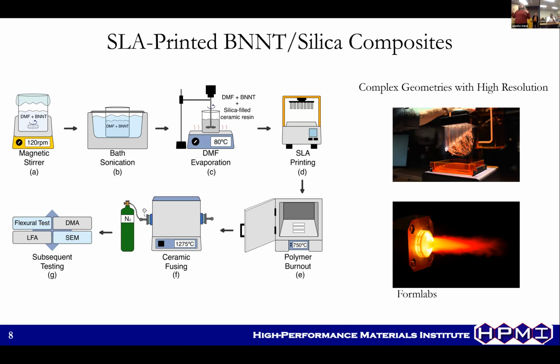But as we increase the content, it will affect the shrinkage. When you 3D print like that, it's an ink that has a UV curable polymer with some kind of particles, like in this case ceramics, and you burn out the UV curable polymers and you're left with whatever particles you had suspended in there. So that itself has its own shrinkage profile. And when you add in another filler to stabilize it, you will change that shrinkage profile in the different directions potentially as well. So at 0.1%, we didn't see any effect. Higher than that, definitely going to see something, but potentially a lower shrinkage.